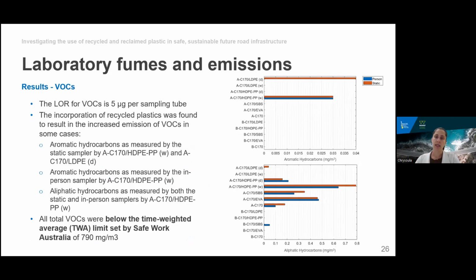In some cases, the VOCs measured by the incorporation of recycled plastics were greater than those of the conventional materials. These were primarily measured during the asphalt mixing activities. For example, we can see that the wet mix using the binder modified with HDPE and polypropylene emitted the greatest concentration of aromatic and aliphatic hydrocarbons as measured by both the static and the in-person samplers, when compared to the asphalt mixing, which was using conventional materials.